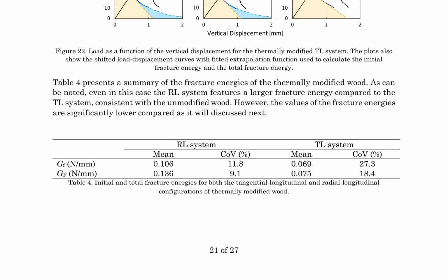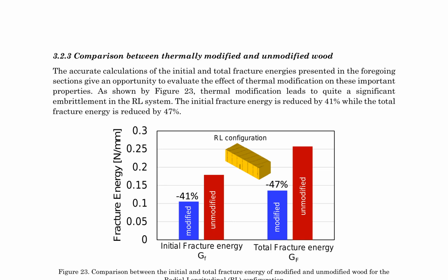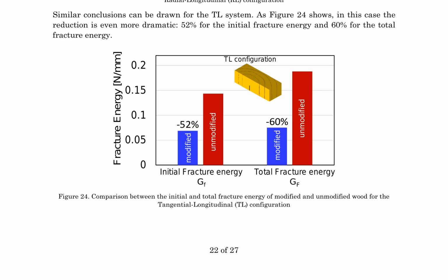Table 4 presents a summary of the fracture energies for thermally modified wood, revealing that the radial-longitudinal (RL) system has a larger fracture energy compared to the TL system, consistent with unmodified wood. However, the values of fracture energies are significantly lower. A comparison between thermally modified and unmodified wood reveals that thermal modification leads to significant embrittlement in the RL system, with a 41% reduction in initial fracture energy and a 47% reduction in total fracture energy, as shown in Figure 23. Similarly, for the TL system, the reduction is even more dramatic, with a 52% decrease in initial fracture energy and a 60% decrease in total fracture energy, as depicted in Figure 24. These findings highlight the significant impact of thermal modification on the fracture properties of wood.